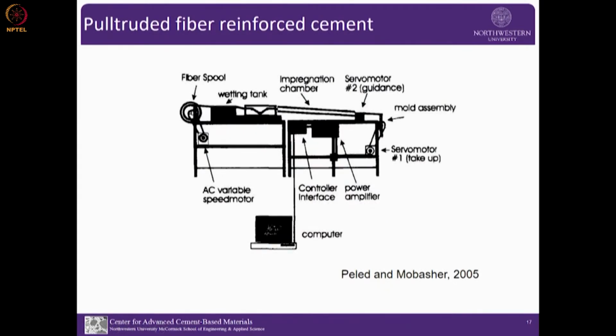So then there are other ways to manufacture, and Alva and Barzin Mobasher at Arizona State are using pultrusion. Now pultrusion is quite common for resin and epoxy type of composite, but this is the first time with cement. So you have a continuous strand, it goes through the cement slurry, and then you develop the composites.